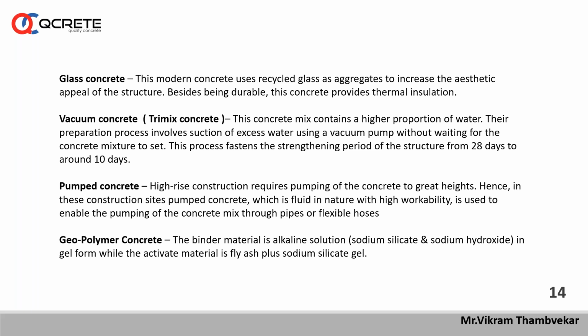So adding more water in concrete and then removing this water after some time, you are making a number of pores in that vacuum concrete floor area, from the concrete which is used for this flooring purpose. So this technology of vacuum concrete is not much advisable, of course. Then pump concrete. Pump concrete requires a slump of minimum 150 and a maximum up to 250, 300, 400, depending on the length of piping and height of piping or the structure where you are placing the concrete. Especially for this pumping concrete, I want to tell our friends to avoid